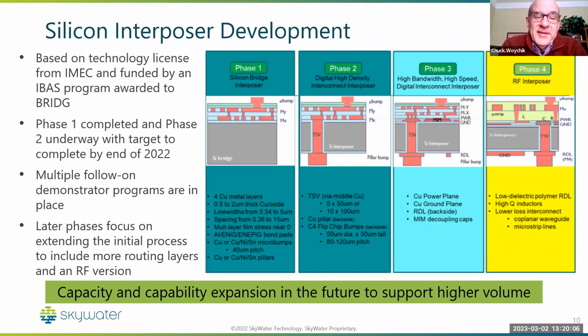A silicon substrate. This is fully qualified. It's available right now. This leads into phase 2, which has the same buildup structure, but now we include a 10 by 100 micron TSV, and this will be fully qualified by the end of the second quarter this year. So what we'll have now is phase 1, a bridge interposer, and phase 2, a TSV based interposer, available by the middle of this year. And I just want to mention the finest lines are 1 micron lines on this interposer.